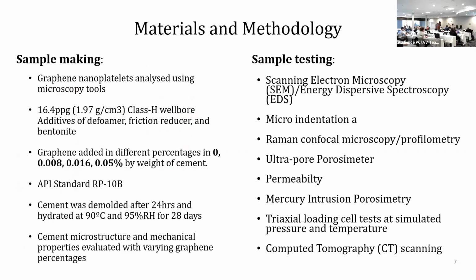So what did we do? We tried to see how this would work for a plugging and abandonment project in the Gulf of Mexico. We made a 16.4 density cement slurry, following API class H, and we played with 3 different concentrations. The first one, 0.008, is what is reported in cement and concrete research as a good number, but we thought, let's push it a little bit further and see what happens. We cured our samples at 90 C for 28 days. Those are temperatures relevant to the Gulf of Mexico.